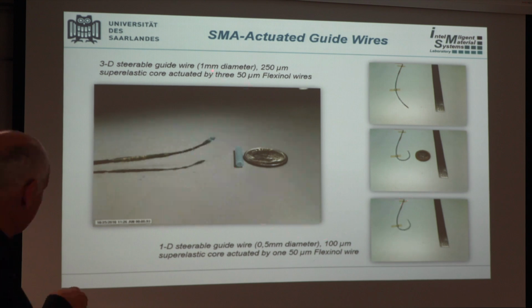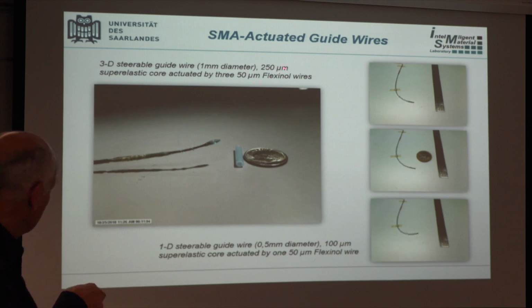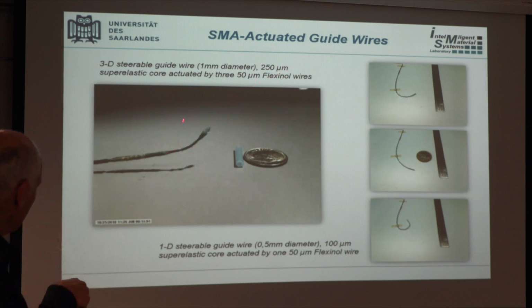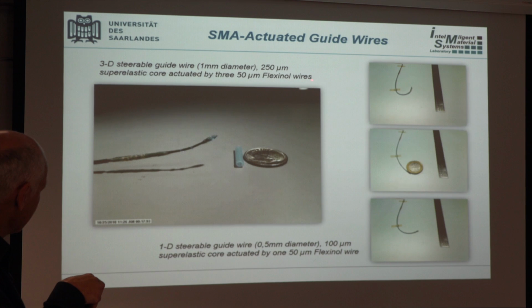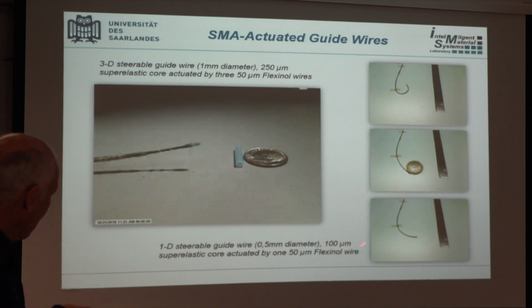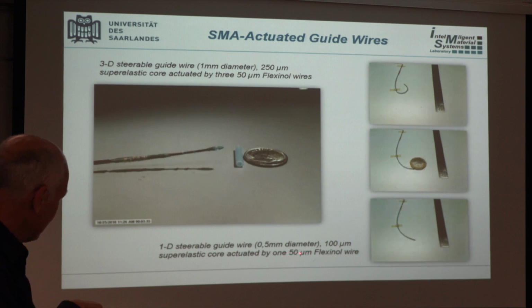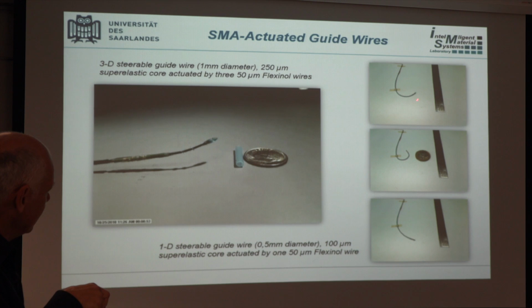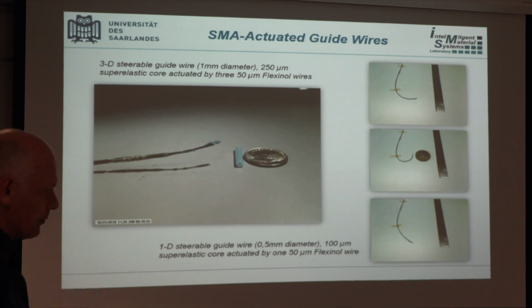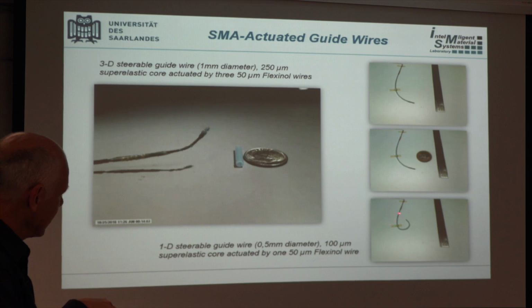So here you see the dimensions: 1 millimeter in diameter, 250 micrometer super elastic shape memory alloy actuated by 50 micron Flexinol wires. Here is a 100 micrometer core of a super elastic wire, and it's actuated by one 50 micrometer muscle wire. And you see that you get a huge amount of deformation from that one wire. So you can basically have the tip bend back onto itself.